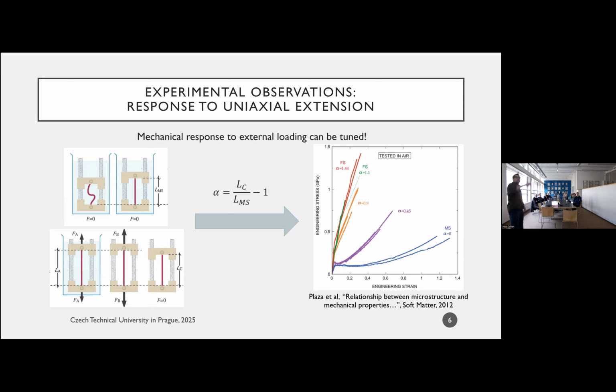Once the fiber is dry, I can pull it out. I can look at its length in the dry state, so we'll call that LC. LMS is the length of the fiber in the supercontracted state. And then I can define this alpha parameter, which we call the alignment parameter, because it tells me something about the microstructure. And then test it. You can see that if I do this process, I can end up with a lot of different properties. Typically, if I want toughness, that comes at the expense of extensibility. So I can have fibers that are very extensible but weaker, or fibers that are less extensible but much stronger. That's the interplay here.